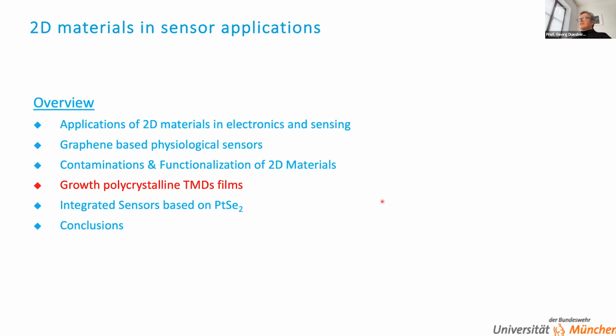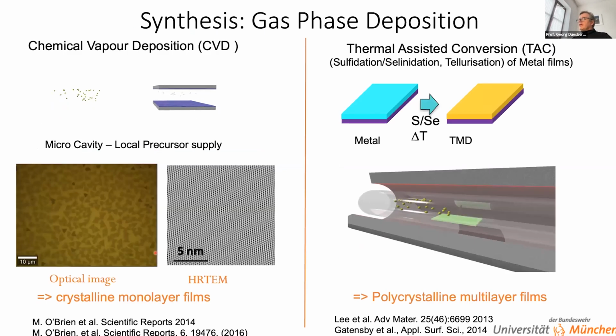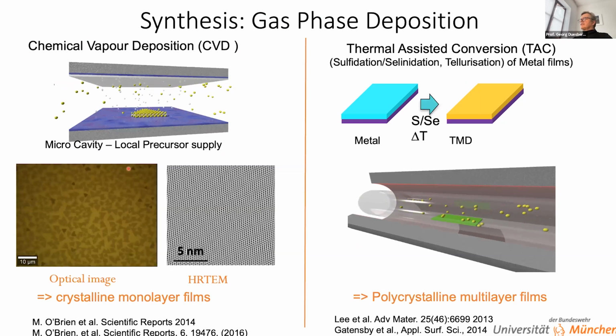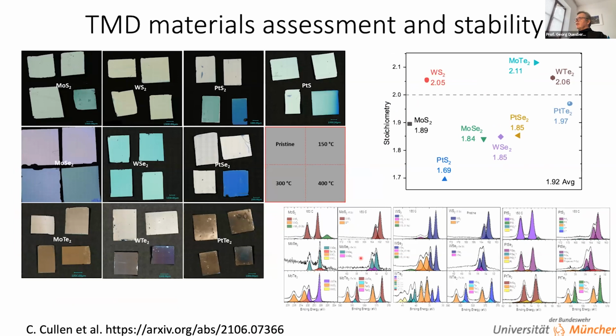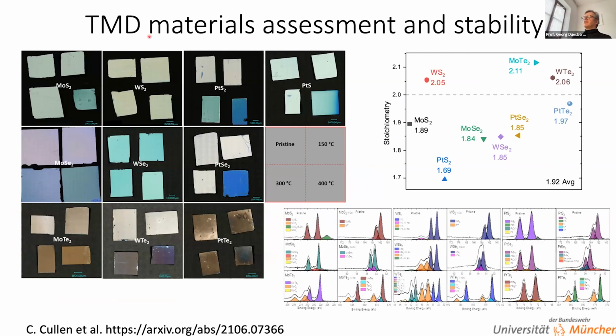With this, I would like to switch gears and talk a little bit about polycrystalline TMD films and some sensors or detectors we made with those. As mentioned before, I'm not talking about this nice monolayer growth as shown before. I'm talking here about materials which we sputter or evaporate on top and then run sulfur or selenium over it and convert it to transition metal dichalcogenides. It's a relatively facile, easy to use method, and we've been working with this for quite a while, and we've been synthesizing quite a wide range of TMD materials with these methods.